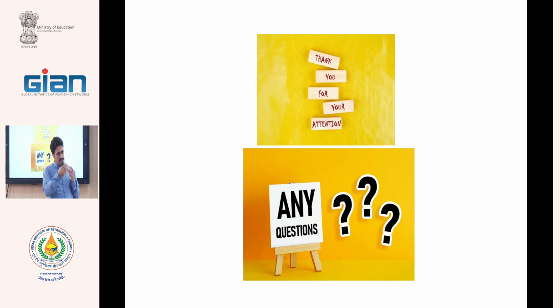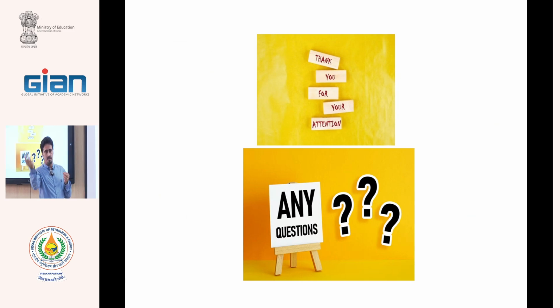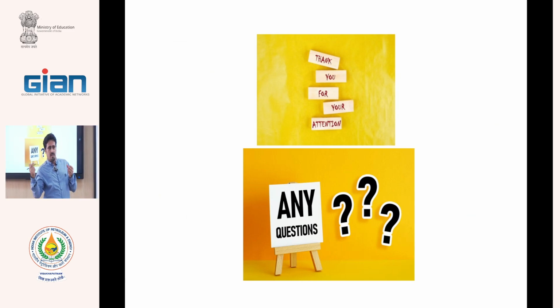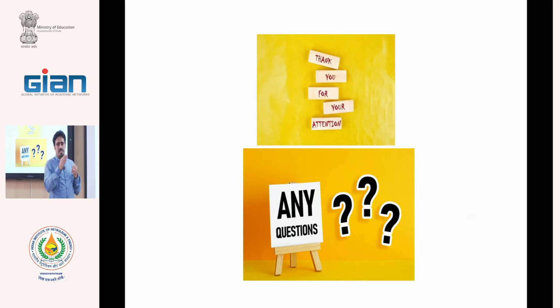For example, we have air, and in air we have nitrogen, argon, and oxygen. When we have an electrical discharge, in this electrical discharge we force the oxygen to give one electron to the electric field. And when it gives one electron to another, we produce a radical. Therefore, we have a nitrogen radical and an oxygen radical. Nitrogen reacts with oxygen and produces nitrogen oxide radicals and others.